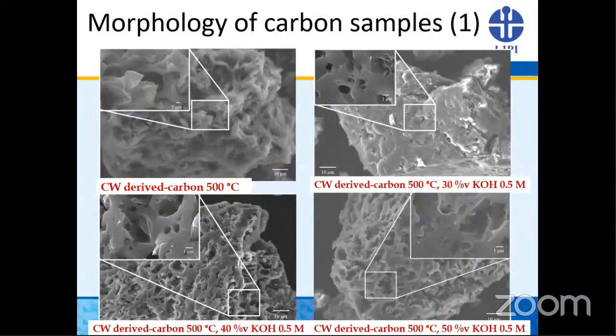And we also, after carbonization, we conduct the treatment using solvothermal in autoclave, and after that we compare the morphology of the carbon sample. Here we can see the morphology of the carbonized sample at 500 degrees C. The texture morphology is already obtained, but after we treat it in the solvothermal method, the pore has been opened. Not similar with when we compare with the carbonized sample. But if we compare, we also make some variation the amount of solvent.